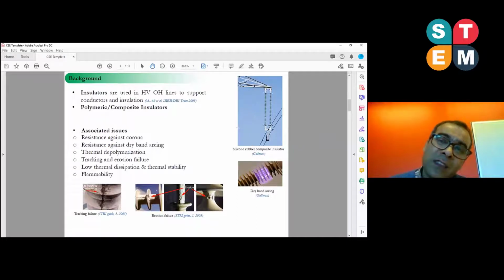There are several issues with polymeric insulators when they work in an outdoor atmosphere. One major problem is corona, which is a plasma composed of electronic species and UV light that can deteriorate the polymeric material. Another problem is that with the passage of service, pollution accumulates on the surface of the insulators. In the presence of some moisture, or even sometimes light rain, that can initiate electrical dry band arcing due to high leakage current on the surface. That high leakage current can easily increase the surface temperature, and that temperature can thermally depolymerize the polymeric surface.